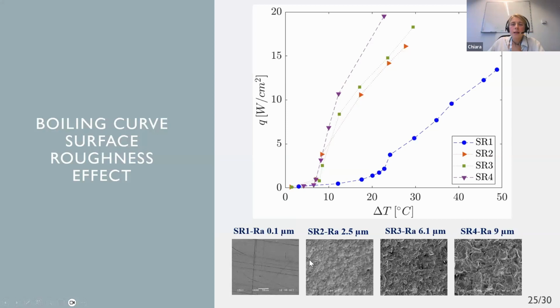So now I'm comparing simply the sandblasted samples. And we can see that compared to the smooth sample, that is the blue curve, increasing roughness clearly has an impact on the boiling curve. First of all, the onset of boiling is anticipated from around 20 degrees C of superheat to below 10. This means that our electronics can operate at lower temperature if we want to use a two-phase flow. And also the critical heat flux limit, that is the last point of these curves.